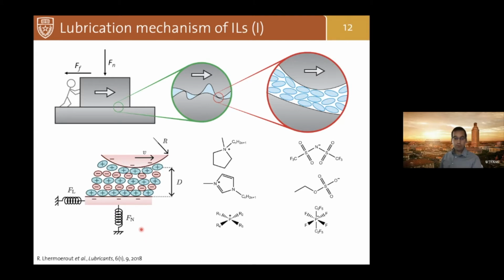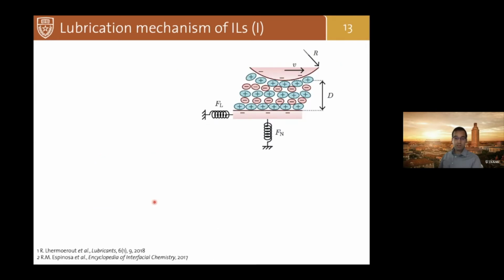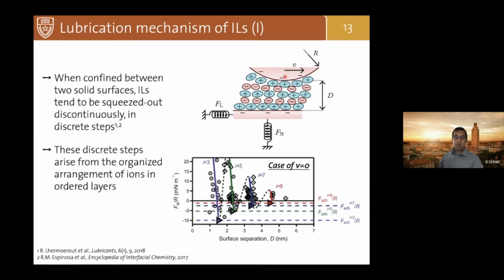A lot of people use nanoscale devices, such as the surface force apparatus and the atomic force microscope, to squeeze the ionic liquid between the surfaces, trying to understand what happens to the ionic liquid when it is confined between these two solid surfaces. So published literature shows that when you have velocity equal to 0, meaning that they are static, you're just compressing the two surfaces and confining the ionic liquid, you have what is called progressive squeezing out of the ionic liquid.